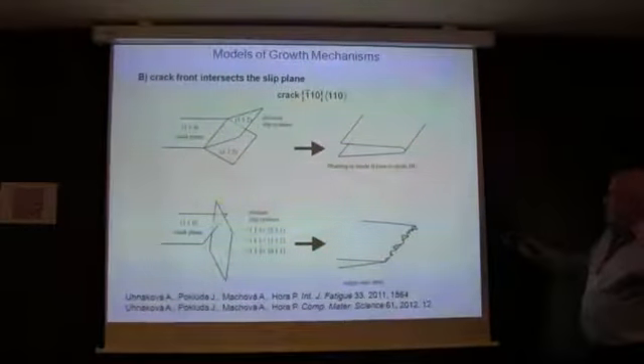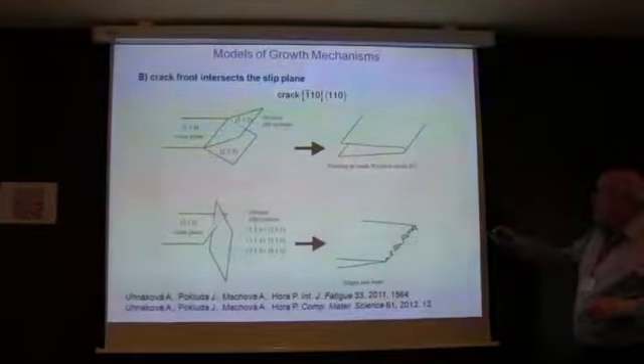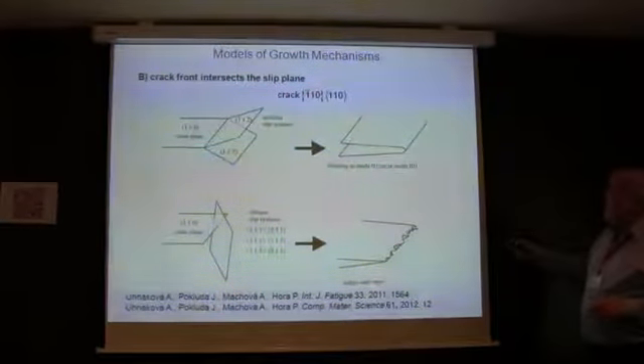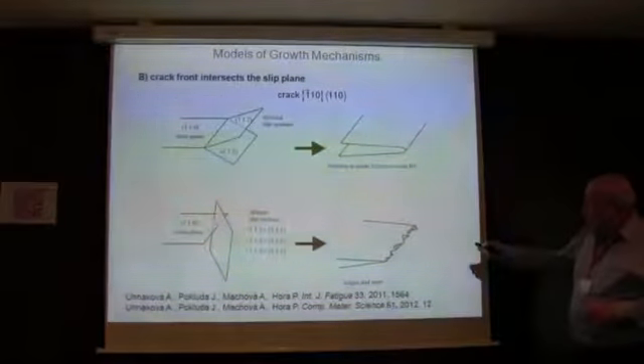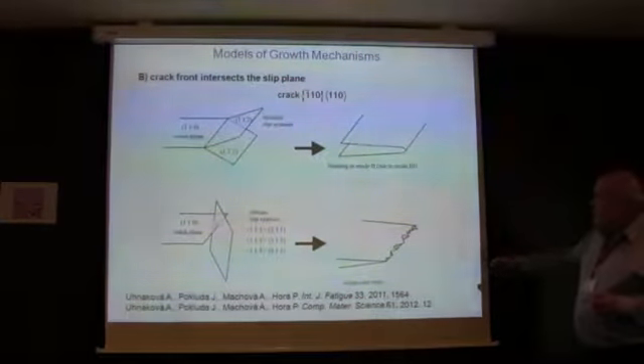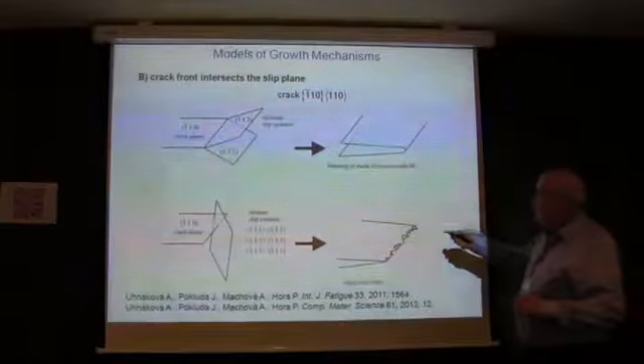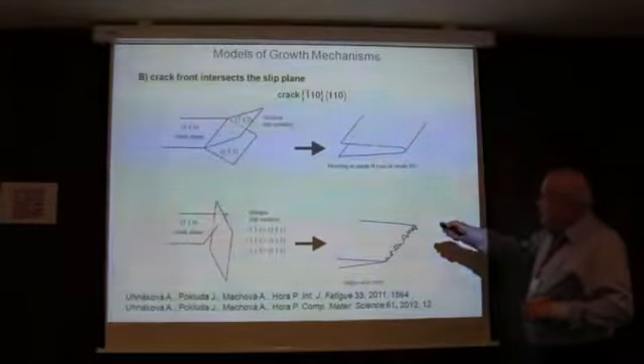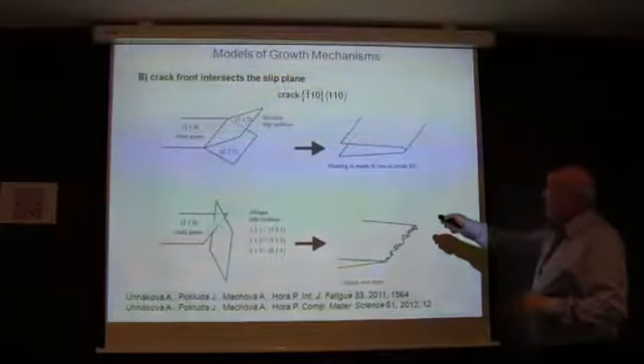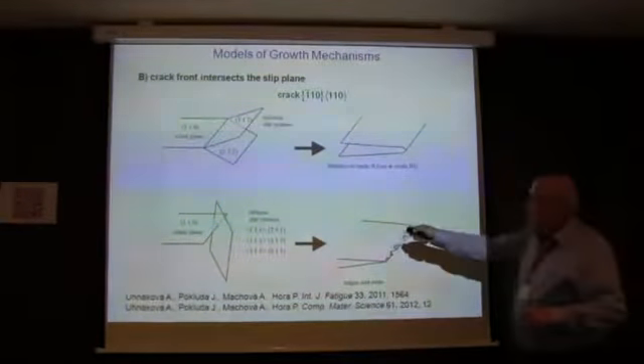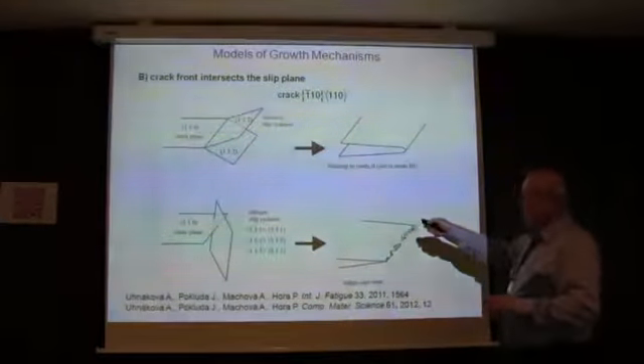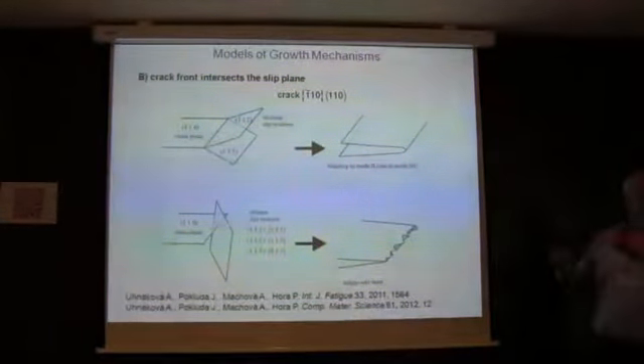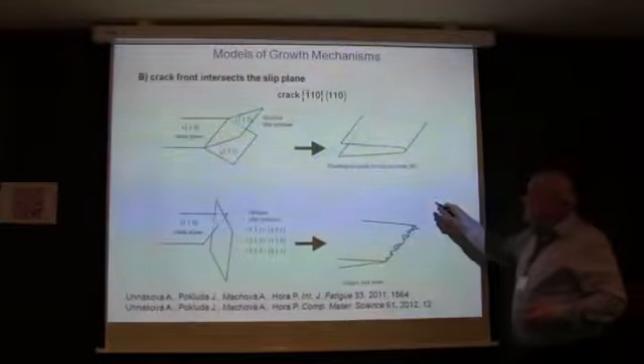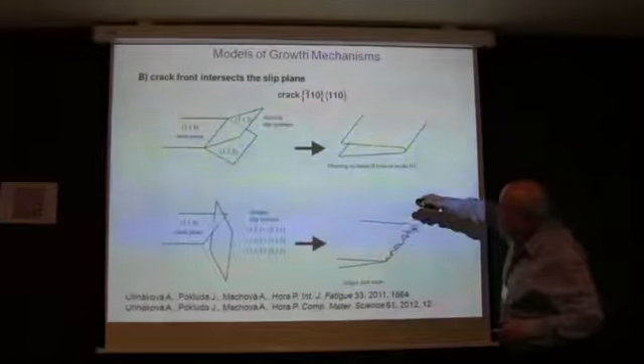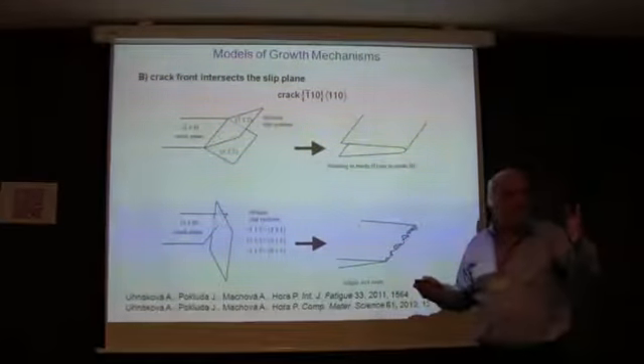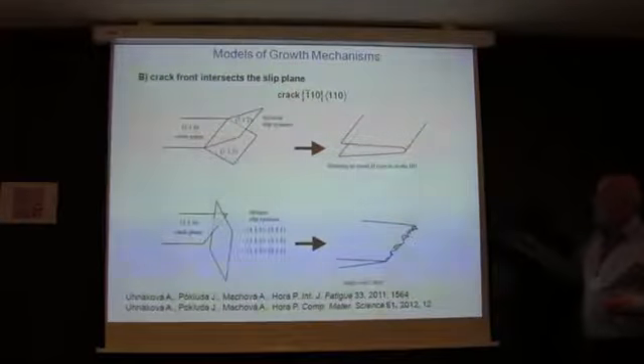And so we analyzed this more difficult case, a crack like this. If you have a crack plane minus 1, 1, for example, you have two possibilities for shear cracks. This is mode 2. You have two slip systems inclined like this, and you apply the shear like this. In this case, you can get blunting, as in mode 1. But this is not possible in mode 3, because the shear is applied like this, and the Schmid factor is 0. So this is not possible in mode 3.